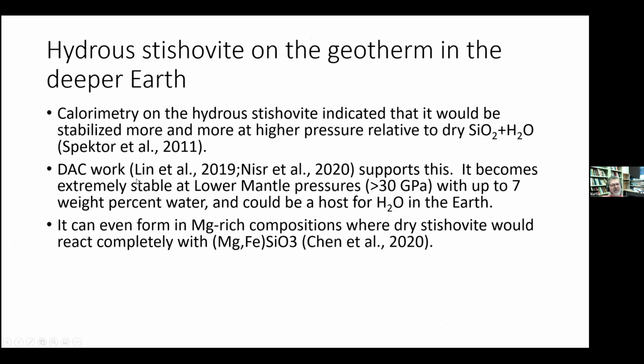And since then, the diamond cell work by Lin at Geophysical Lab and Nisr at ASU found much more water, and in particular, I was involved with this work with Nisr, and we would decompress each sample after laser heating and look at the zero pressure lattice parameters, and that's where we got our water contents. And we got up to 7 or 7.5 weight% in our laser heated samples from anything over 30 GPa, basically. So just out of reach of typical multi-anvils, but soon I think we or somebody else will be able to make